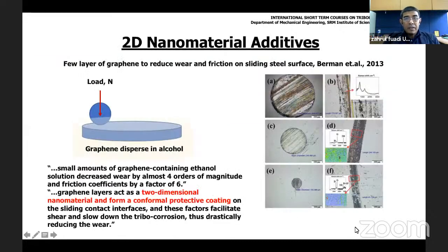And here are some results: graphene can be dispersed in alcohol, and a few layers of graphene can be formed on the contact interface. In this case, a small amount of graphene-containing ethanol decreases the wear by almost 4 orders of magnitude and the friction coefficient by a factor of 6. So the graphene layer, as a two-dimensional nanomaterial, forms a conformal protective coating on the sliding contact interface.